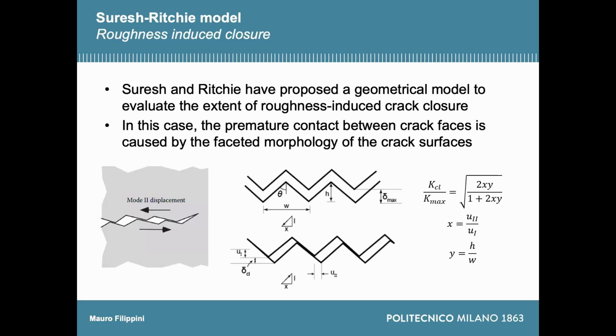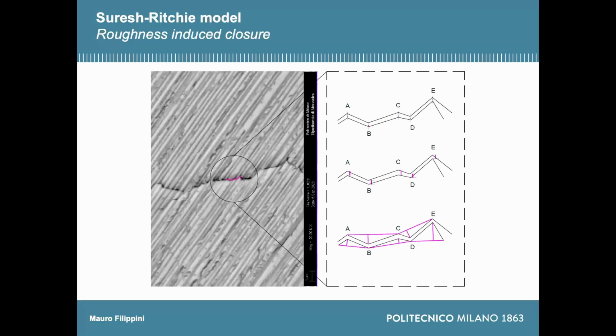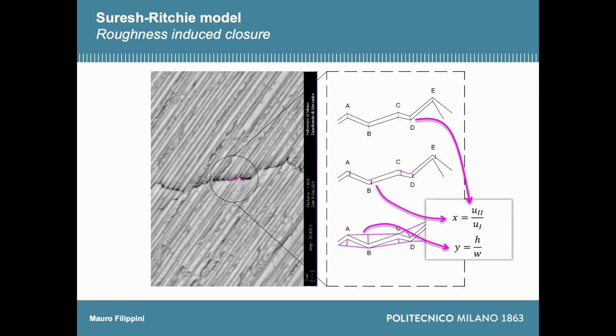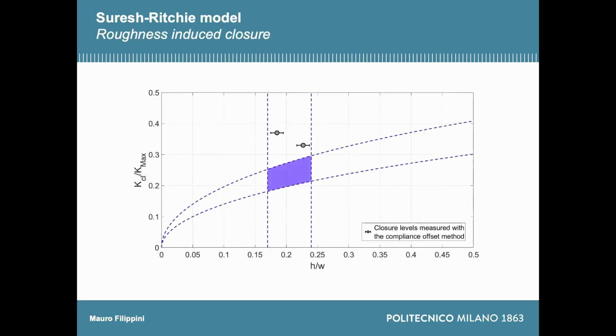which is remarkable. So we tried to apply some modeling of this crack closure phenomenon by using the Suresh-Ritchie model, which is a geometric model. It's very old, so I will not detail that. It's basically that you have to take pictures of your propagating crack and try to correlate this value in a statistical way to the parameters of the model. And by using this model, you can assess that your closure, according to the pictures, would lie into this blue area, but the actual measurement based on the offset compliance method gives you a higher closure level.